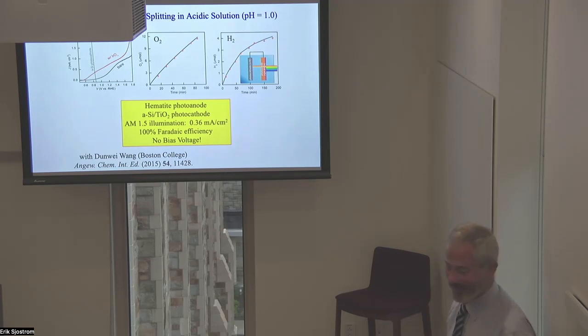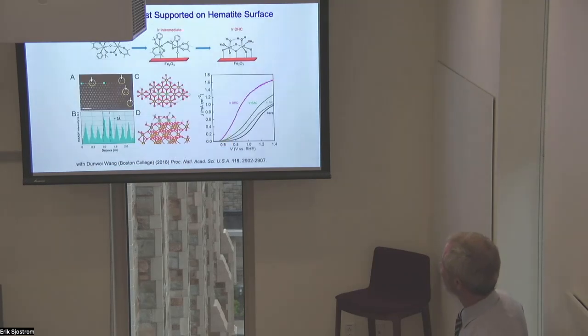So this is exciting. And it works at pH 1, which is really one of the holy grails for water oxidation, to have systems that work under acidic pH. That's because oxidizing water creates protons, which drives the system toward acidic pH. So if it doesn't last under acidic conditions, you might have trouble doing photochemical water oxidation.